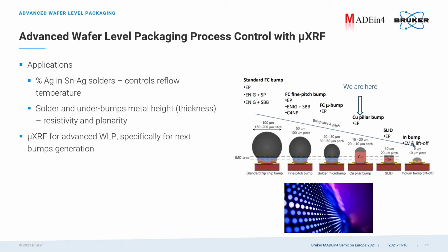The last example comes from wafer level packaging. As you may know, lead-free solder bumps are now commonly used. And these consist of an alloy of tin and a little bit of silver, typically a few percent. The silver content has an influence on the bump reflow temperature, and therefore it is important to monitor it routinely. Also, under-bump metal thickness must be monitored. So this can all be done with micro XRF. One of its key advantages is that it can measure single bumps.